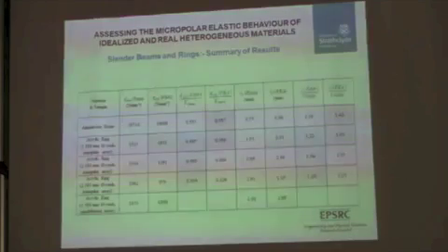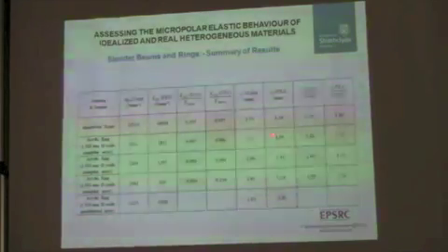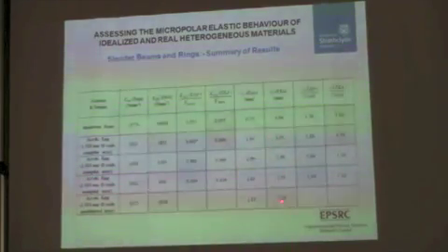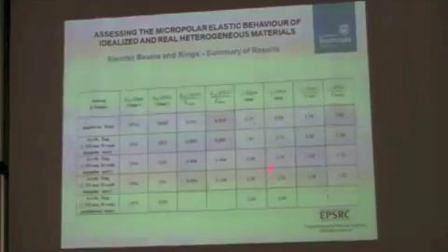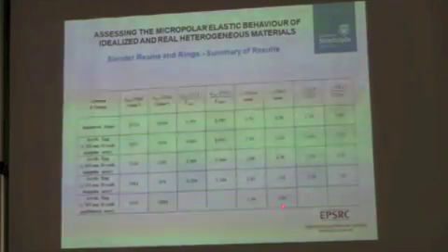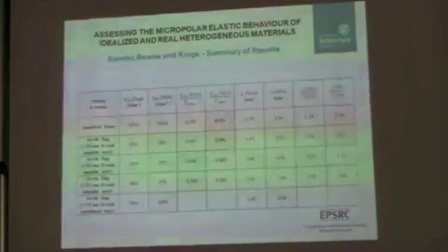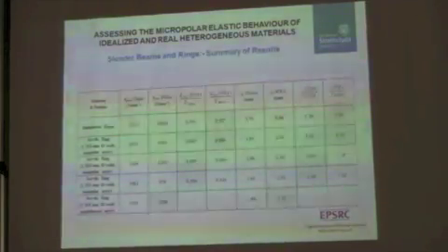The final point to notice is if I compare this data, where I've got the voids arranged on a triangular array, with the case where I've got them arranged on a quadrilateral array, you can see that the length scale parameter is fairly insensitive to the matrix topology.